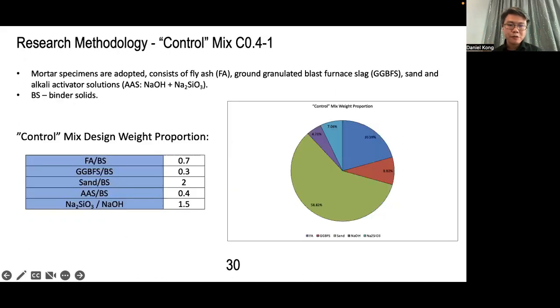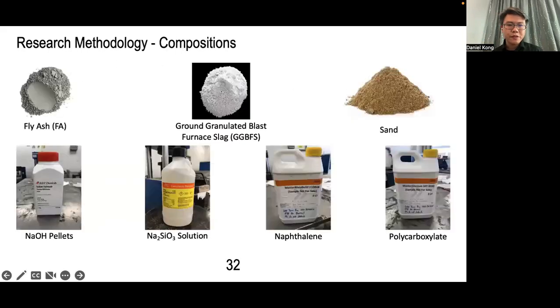Okay, so this is just a small project where we look at different mix designs to try to improve the composition. We use naphthalene-based plasticizers and also polycarboxylic plasticizers to see whether we can. These are just conventional plasticizers that we normally put into cement, and we see whether we can tweak it and utilize it with a pure geopolymer-based application.